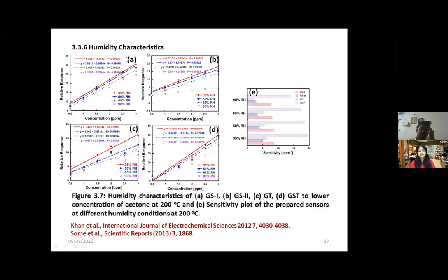And next, we wanted to ensure how the sensor responds to humidity. As the humidity increases, the response of all four sensors decreases. This is attributed to the competition of adsorption between the acetone as well as humidity. There are numerous other reasons why the sensor response decreases in the presence of humidity, which we will discuss further.